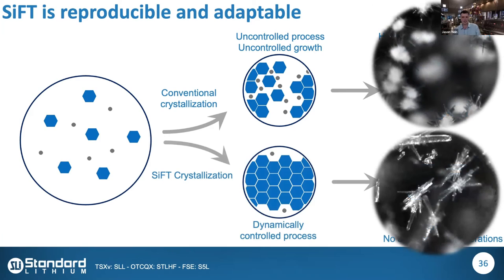So visualizing it with the in-situ microscope is one of the ways we can tell if we're on base or not. If you just go through a standard crystallization, this is what we see visually: these puffballs, these dense cores with these spires. That's what we can tell is a highly agglomerated and impure material. Versus if we do the proper controlled crystallization, we end up with these relatively long aspect needles. Filtering is easier with them, and we also have these exposed surface areas, so we don't end up with inclusions like this.